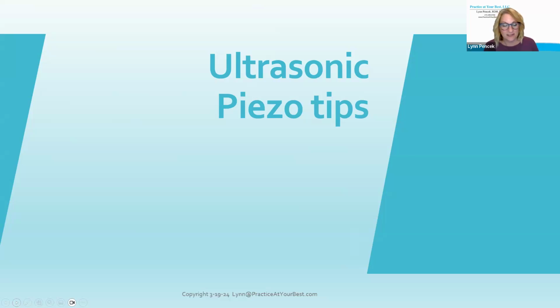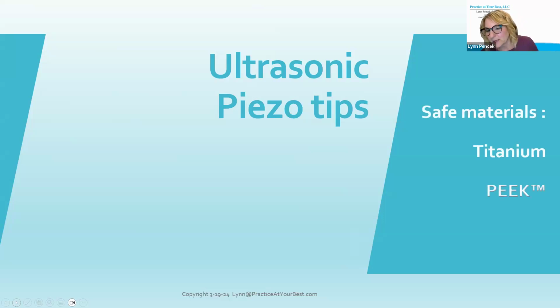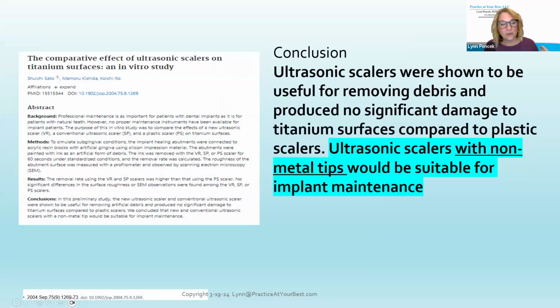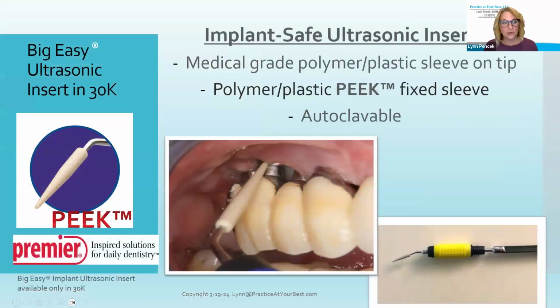So let's talk about ultrasonics and piezo tips. This is a really interesting topic. When we're working with ultrasonic tips, we want to make sure that the tips are made of either titanium or PEEK. PEEK is polyether ether ketone. We don't want to be working with our stainless steel ultrasonic tips on implants because the stainless steel can cause gouging. This was a comparison of different ultrasonic tips in an in vitro study, and the ultrasonic scalers with non-metal tips were more suitable for implant maintenance, for exactly what we just said: the stainless steel can gouge.